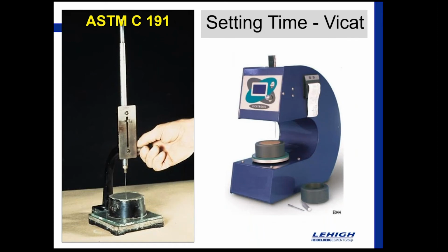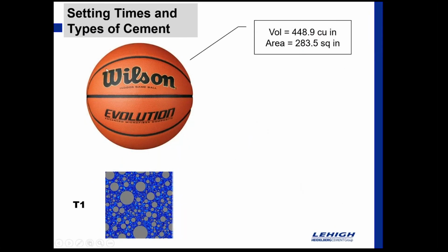ASTM C 191 gives us the setting time information. And this, again, is a time of set test for paste. Well, actually, we're making a mortar out of this, and as the mortar stiffens, the needle will penetrate less. So that's what we're looking at, and there's a point in there where that would reach initial set. So I wanted to spend a couple of minutes and just start to talk about setting times and types of cement and what this all means, and then move this toward a practical application.